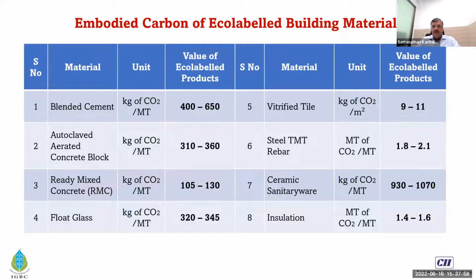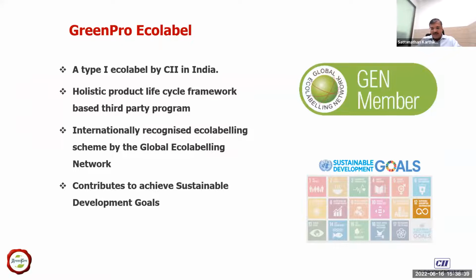Our submission to you all is, please make use of the actual carbon footprint of our Indian product manufacturers. Because, for example, if you take cement, typically they use close to about 850 to 900 kg per ton of cement, which is no more valid. Indian cement plants are much, much better. The carbon emission of Indian cement is much, much lower, even compared to European and American cement manufacturers. So my request to you all is, look at the Indian manufacturers' carbon footprint and use it for estimating the carbon footprint of the building. So these are some of the points I just thought of sharing with you.